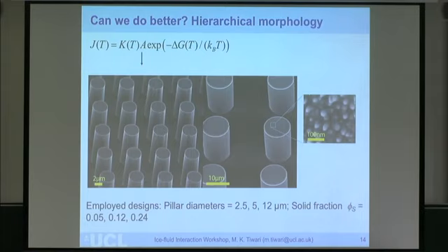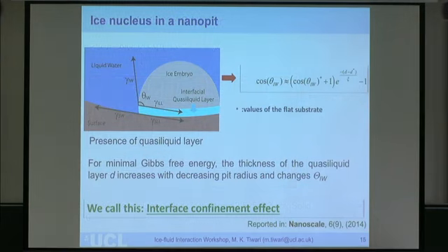And the benefit here is, if you can imagine a droplet sitting on this surface, is sitting on microscale pillars which have nanoscale roughness on top of it. That means the contact area is really reduced, and in this scale here the droplet is quite big. So we can reduce the surface area of contact quite substantially. The picture is not just as simple. I'll skip some of the detail here.